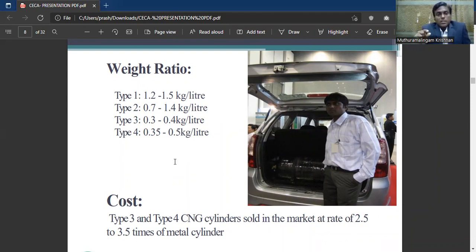The thickness is less for winding. You can make the cylinders in 45 minutes to 1.5 hours, depending on the ratios, like 70-30 or 80-20 or 60-40. The winding time, the manufacturing time, will increase. So this is the way for Type 4. That's why 0.35 to 0.5. Why do we put 0.5 kg per liter? Because of the glass fiber contribution. Whereas in Type 3, because the inner body is a metal liner, you can go with carbon fiber alone.